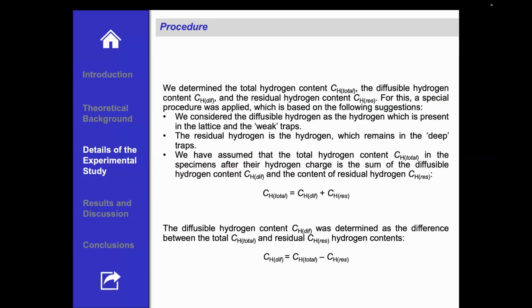We determined the total hydrogen content as the diffusible hydrogen content and the residual hydrogen content. This procedure was applied on the basis of the following assumptions. We consider the diffusible hydrogen as the hydrogen which is present in the lattice and the weak traps. The residual hydrogen is the hydrogen which remains in the deep traps. And we have assumed the total hydrogen content in the specimen after hydrogen charging is the sum of the diffusible hydrogen content and the residual hydrogen content.